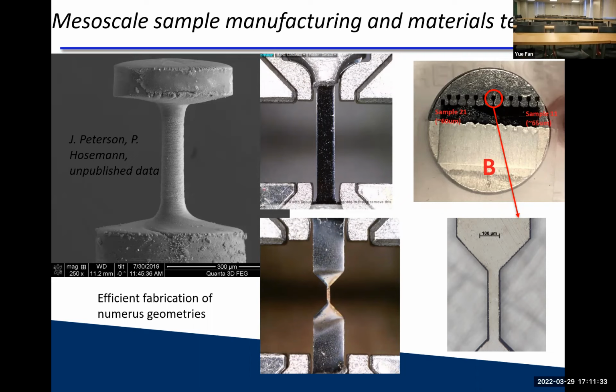So we actually just started doing that with a bulk metallic glass, and did some indentation. We haven't published it, and it's pretty new. There's one poster who came from Jan Schroers' group at Yale, and there's a lot of bulk metallic glass. You got these beautiful bulk metallic glasses, and they're irradiated, helium implanted with the same method, and then indented. And it behaves very different from the crystalline version, very, very different. In fact, what we see is you can see in bulk metallic glasses, you get these slip traces, right? The shear traces, and you can see those. And what happens is the helium bubbles actually line up where those shear traces happen, and they grow in that way. Beautiful thing. And the hypothesis there is it looks something like this.